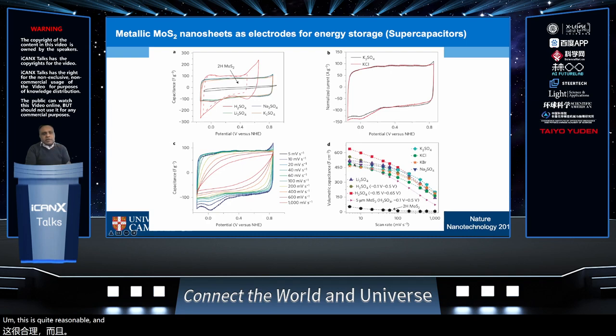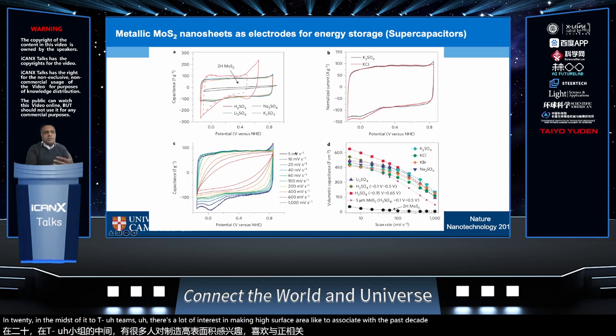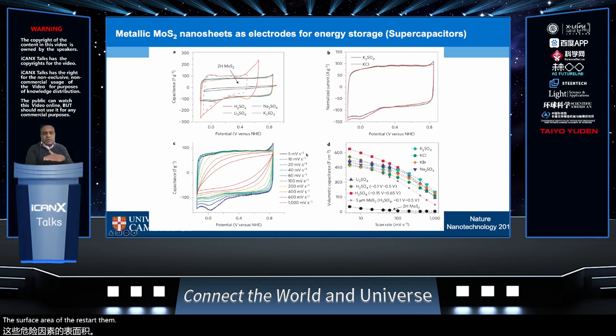And what's interesting about this was that in the mid 20 teens, there was a lot of interest in making high surface area electrodes for supercapacitors. The surface area of these restacked MoS2 is actually quite small. It's on the order of 10 meters squared per gram. But the charge storage is efficient due to intercalation and deintercalation between the sheets. And so because the surface area is quite small, the volumetric capacity is high, right?